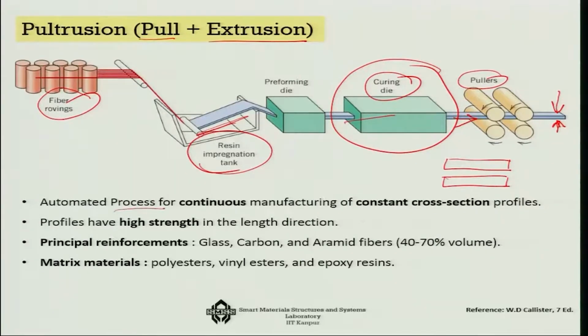So this is an automated process for continuous manufacturing of constant cross section profiles. And the profiles are, in this case, such that the fibers are perfectly aligned. So suppose if this is my plate, then all the fibers are perfectly aligned. That's how you are impregnating them and you are pulling them. So they have a high strength in the length direction. So that's the good part. The principal reinforcements are glass fiber, carbon fiber and aramid fiber, and you can get anywhere from 40 to 70%. 70% is quite a high number for volume fraction.